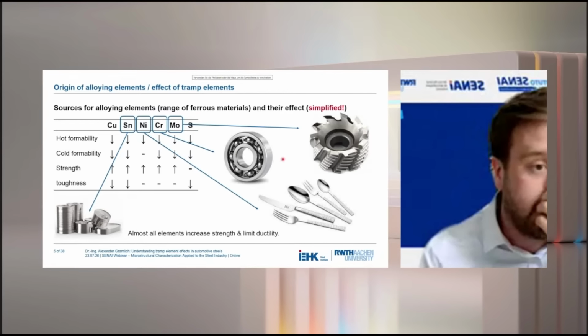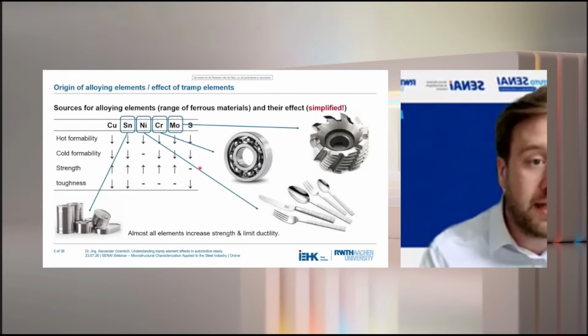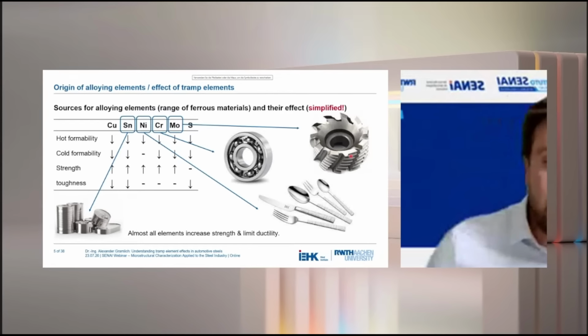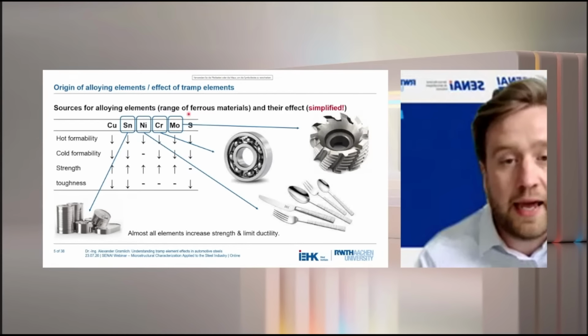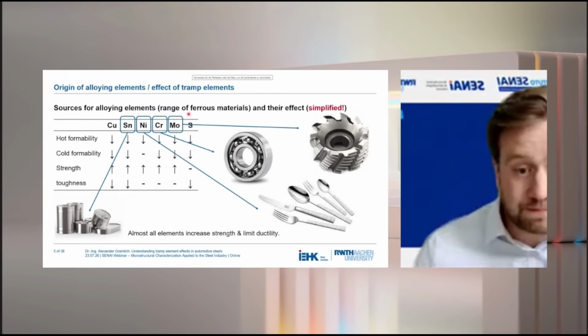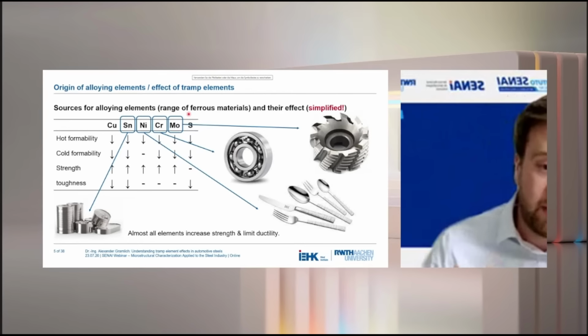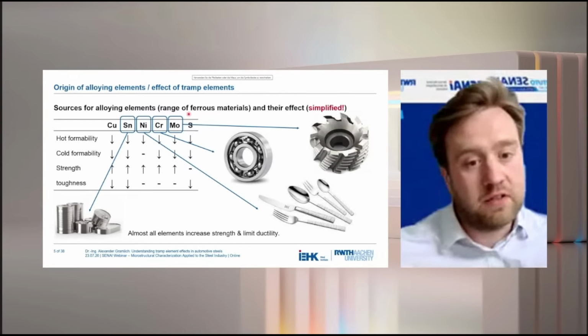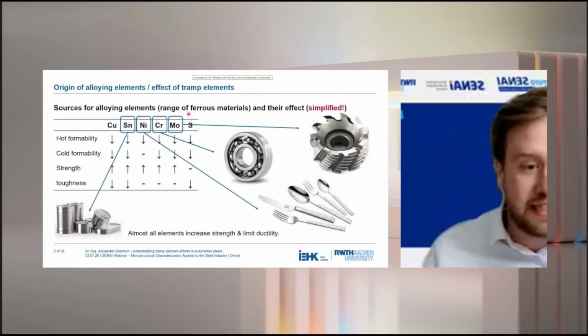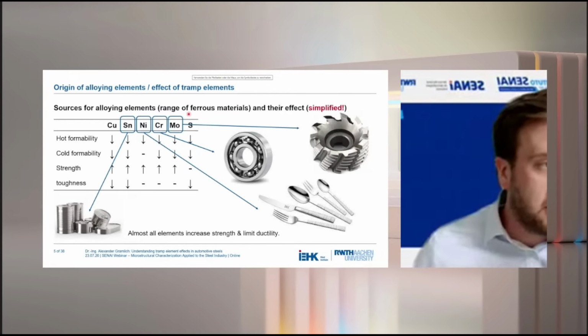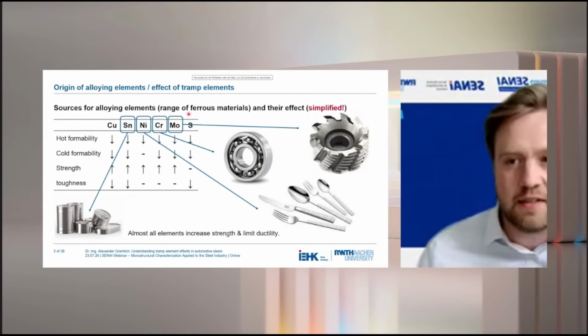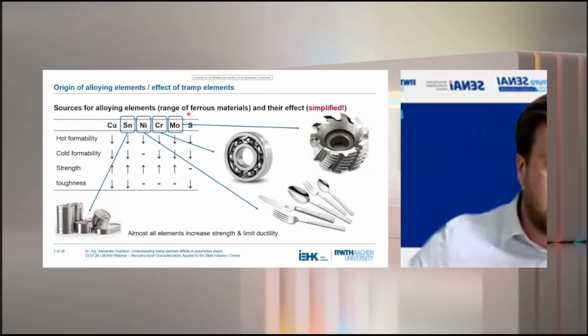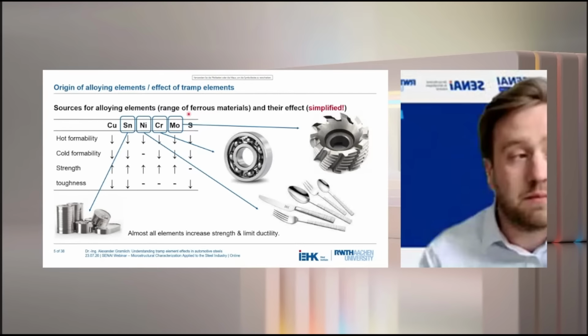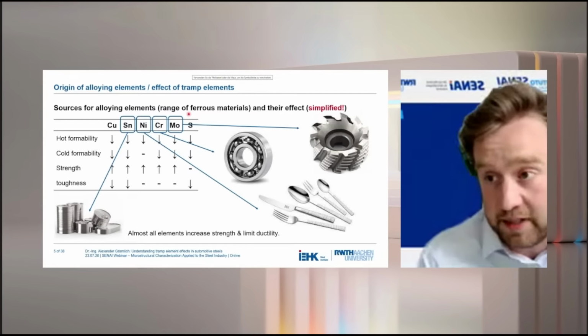I gave some examples here, as you can see, especially when we are talking about bearings or high alloy tool steels, it becomes pretty clear why we also have chromium and molybdenum in our steel scrap. So in summary, most of these tramp elements will, to some extent, increase the strength and limit the ductility. So with this, we could work to some extent. However, this is not everything which is covered by the tramp elements, and we will, especially in the case of copper, see the biggest problem in the upcoming minutes.